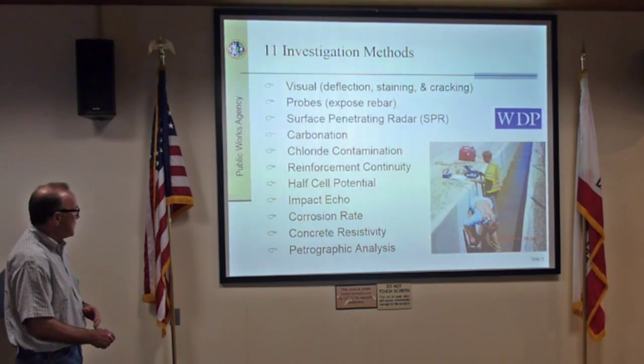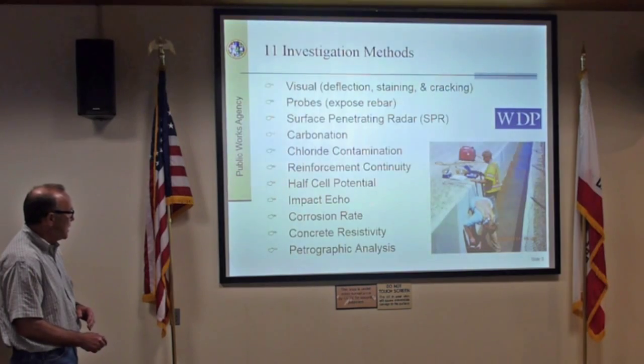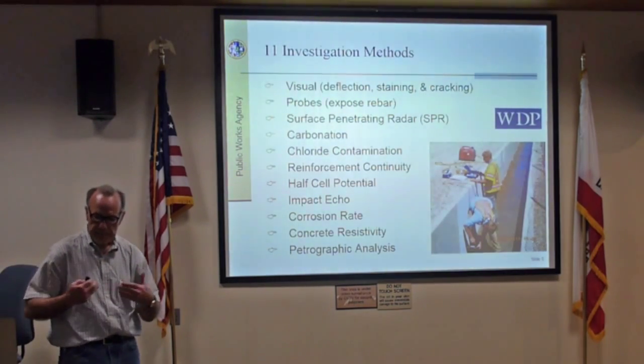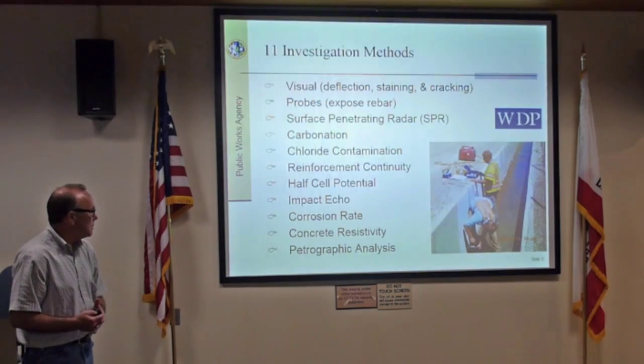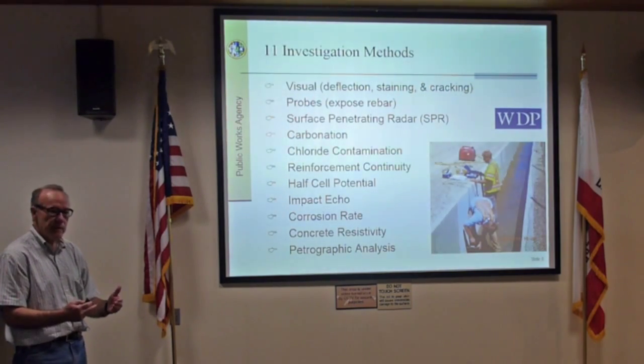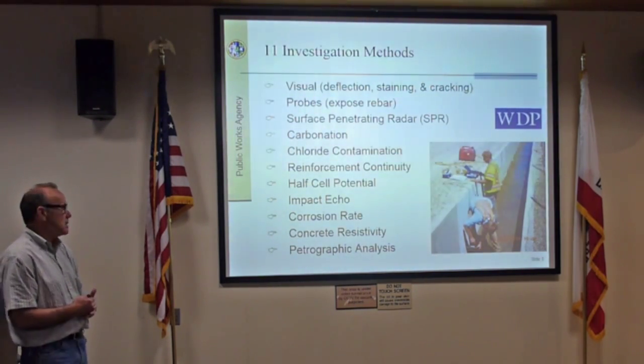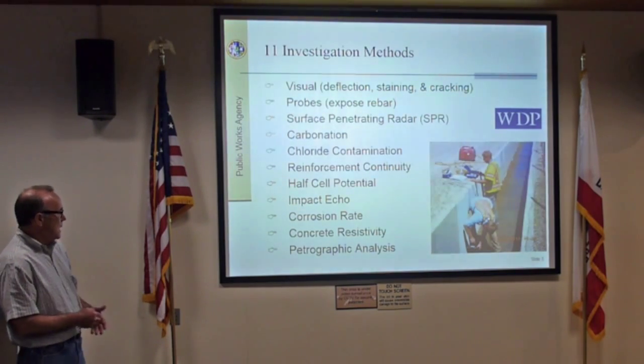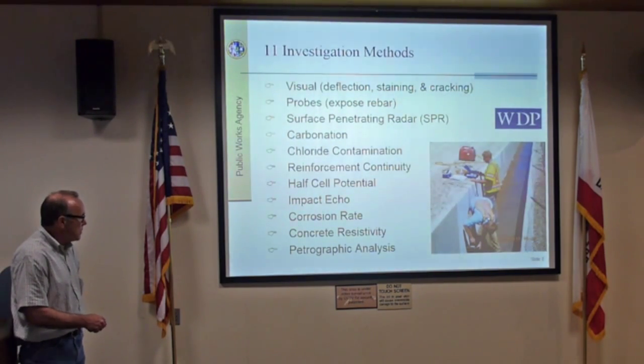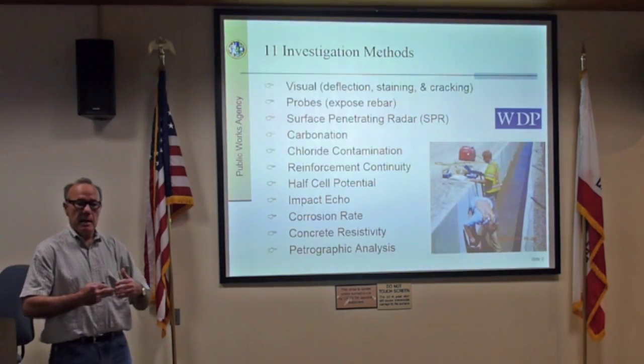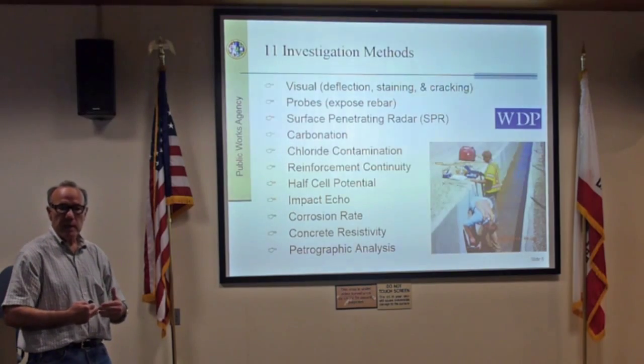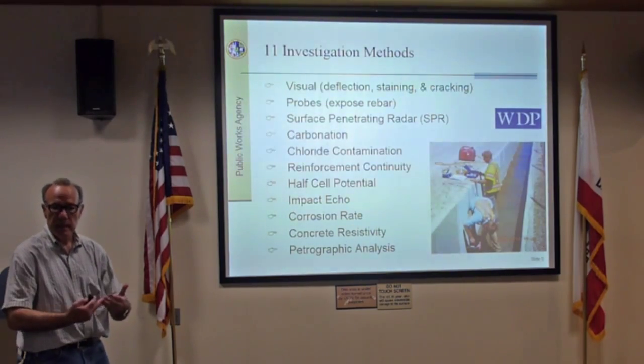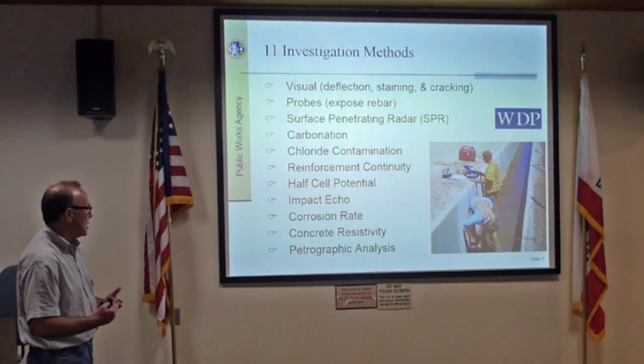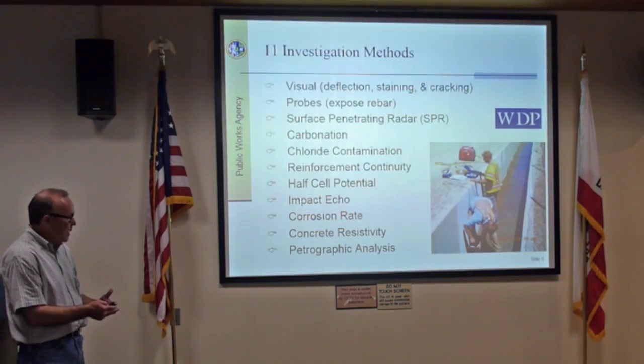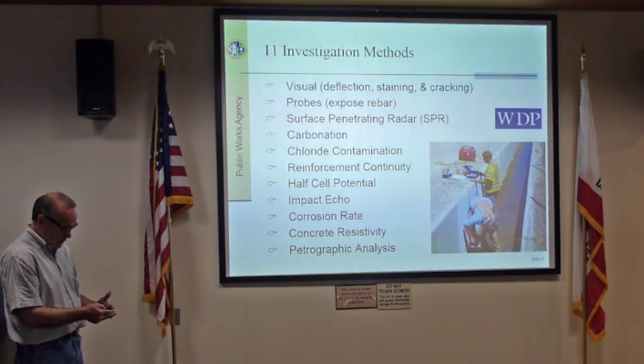There's also a method which we have utilized for over 20 years, Impact Echo. It's a non-destructive method for assessing the integrity of concrete, and we'll show how we use that specifically for corrosion. Also, we can measure in situ concrete resistivity. Since corrosion is an electrochemical process, the more wet the concrete is, the more conductive it is, the higher the potential for corrosion. So again, it's another test, but it doesn't tell the whole story.